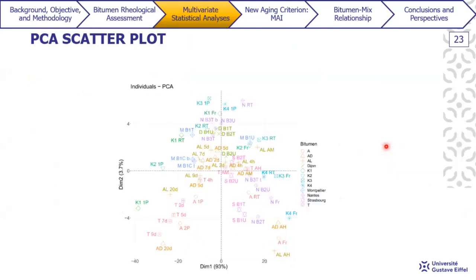So here's one of the results of PCA, which is the PCA scatter plot. And this analysis was done using 59 bitumens. It was actually more than 59 bitumens, because 59 was the number of bitumens supplied by the project. But in this case, I also added more bitumens that I took from the literature review, from some previous work. I just got this data set from these papers. So what we could observe already, I'm gonna explain this graph here, don't worry. Okay, so the increase in the aging level goes from right to left.